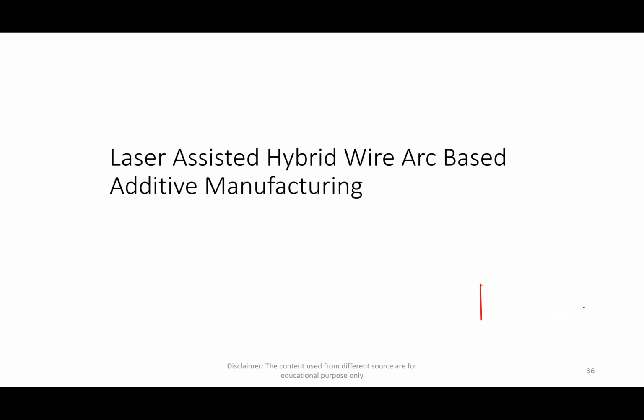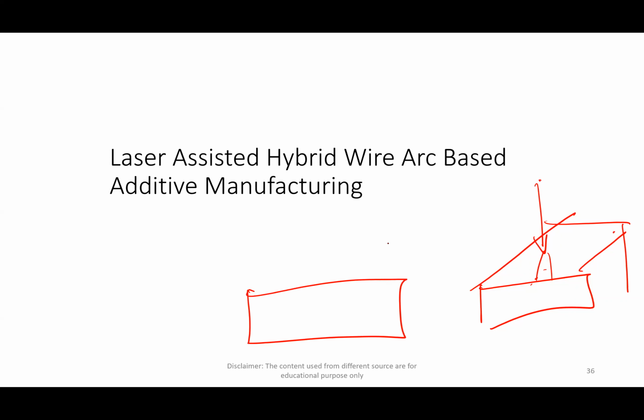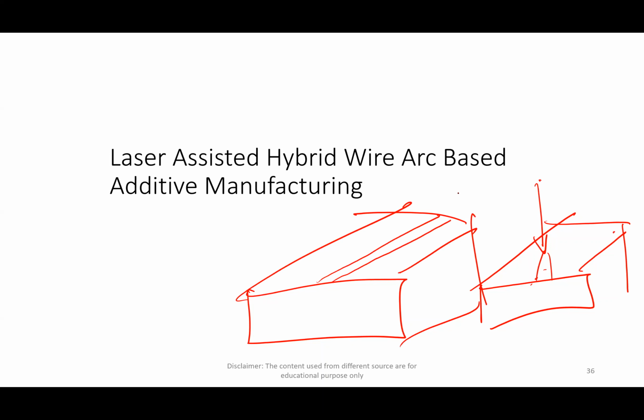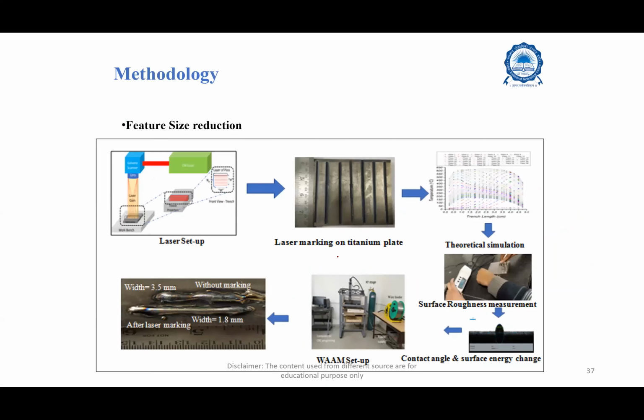As far as this laser assisted system is concerned, in our MIG based welding system, if this is my sample, there is an arc which jumps and tries to deposit. Now, when an arc jumps on the surface, the surface also plays a major role in manipulating my arc. So what I can do is, if I make a small laser marking on this region, then I can somehow concentrate my arc in this region so that I can make thin sections. So with this as an idea, we thought of developing this system.